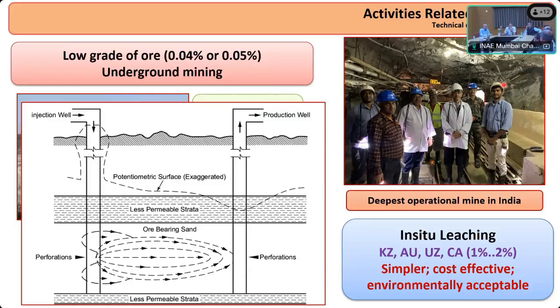If you have uranium in the plus 4 state, it is not dissolvable in anything except in the conditions you want to put in. But if it becomes U plus 6, it becomes soluble in the water. So then it is a dangerous condition, and you have to take care of this part. Once we can master this technology, we can bring down the uranium cost very low, and this does not require the entire setting of the plants. So even for low concentration, small sources can also be exploited.